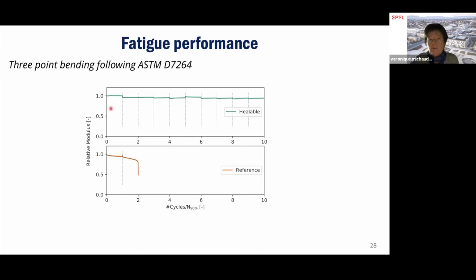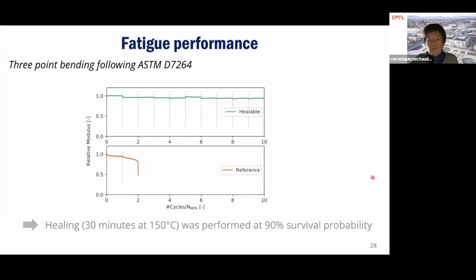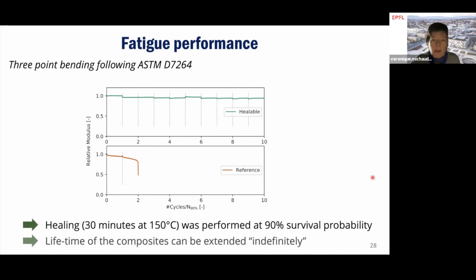With the healable material, we start at 90% survival rate, we put it in the oven, we put it back, and then it went on, put it in the oven and back up to 10 times without ever breaking the material. So our conclusion was that, of course, we can extend the fatigue life indefinitely, which is maybe to be checked, but at least it's a very promising result.